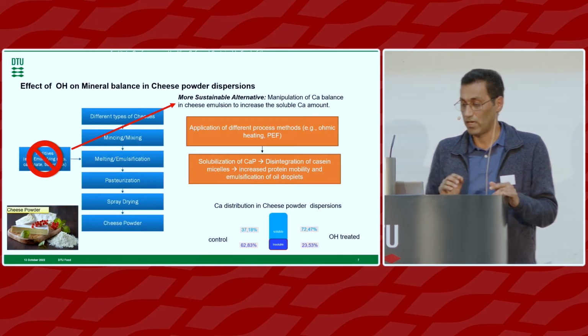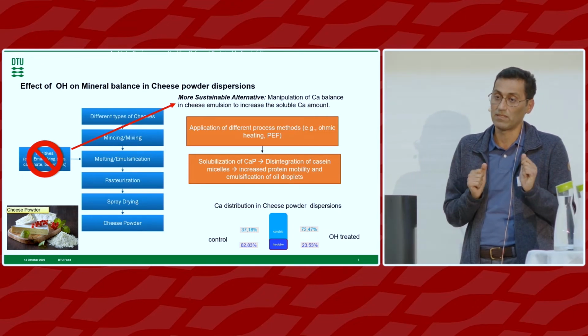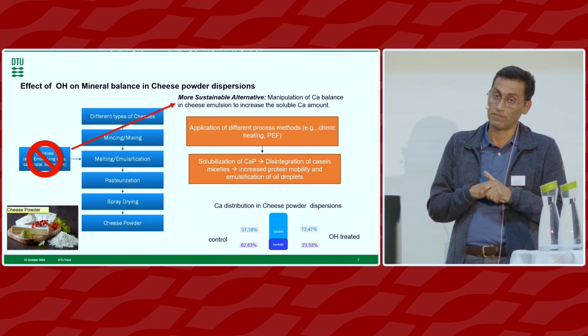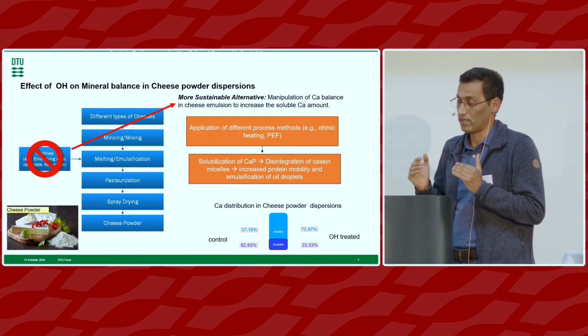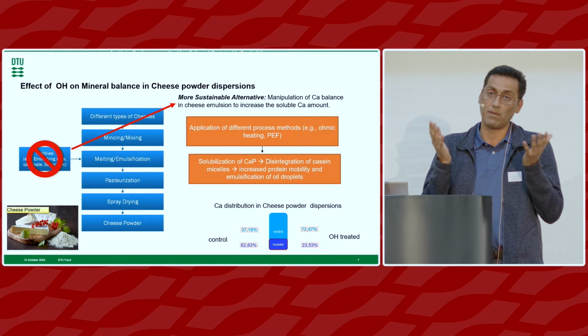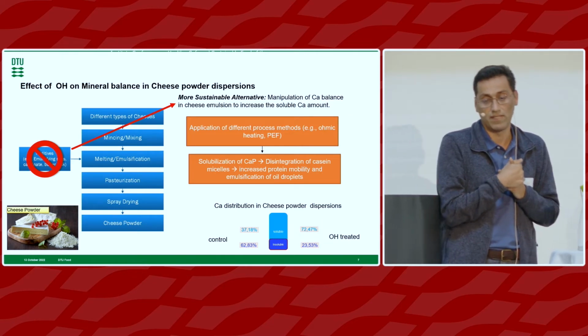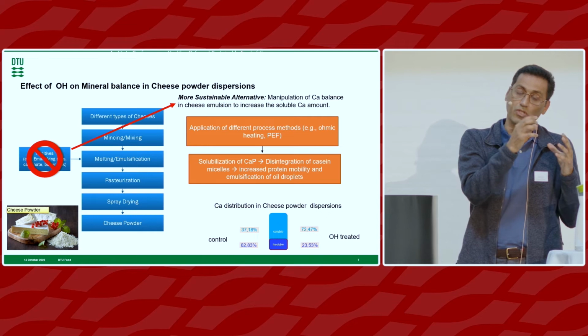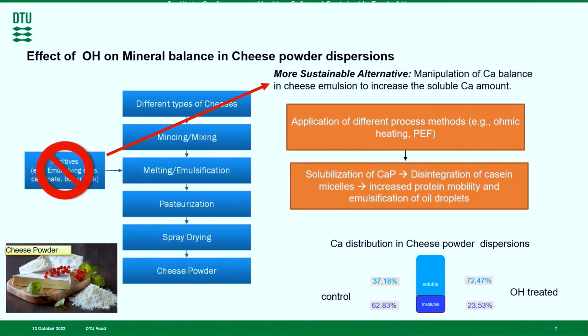Then we moved ahead. We tried to use electric field and heat treatment to change mineral balance in milk. It is important, you know, when you increase temperature, like in sterilization or pasteurization, you are forcing calcium to go to the micelle, and then all the functional properties of micelle will disappear. If you want to have a good emulsification, it's impossible then. Because when you remove calcium, micelle will be disintegrated. Proteins are available to act at the interface. So this is important. We wanted to increase temperature, but still have some soluble calcium.